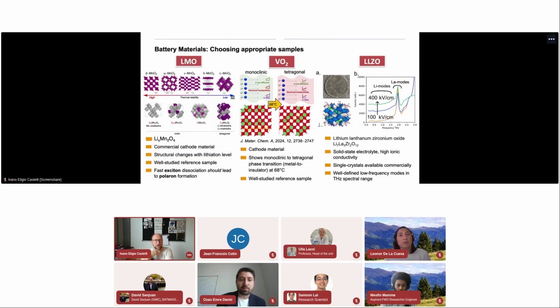Again, vanadium oxide is another important cathode material, a very well-referenced example, and it also shows a phase transition at this point. And then the lithium lanthanum zirconium oxide, a solid-state electrolyte with good ionic conductivity. The single crystals are available commercially, so it's a material we can actually test in a very accurate way.